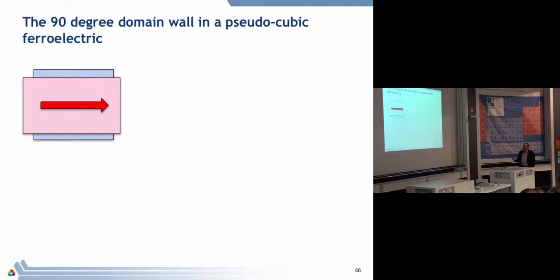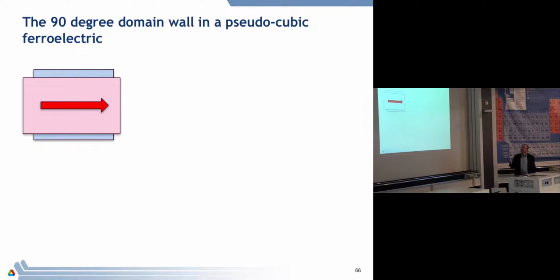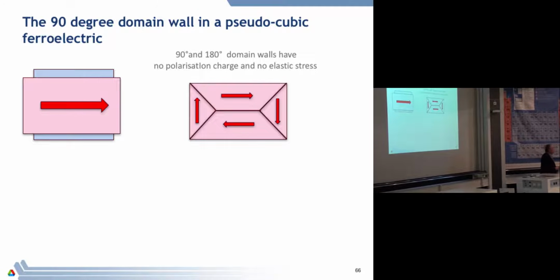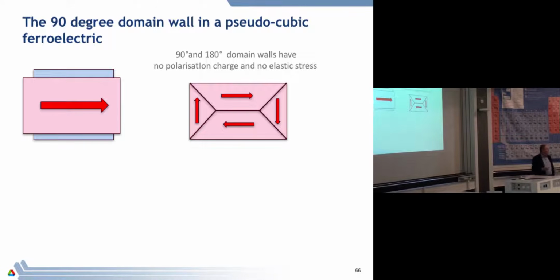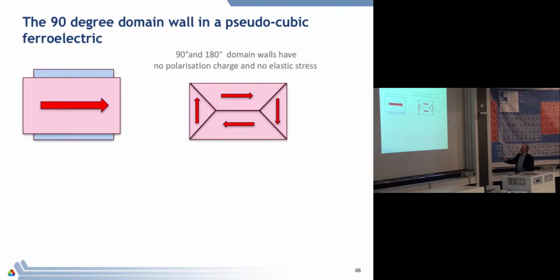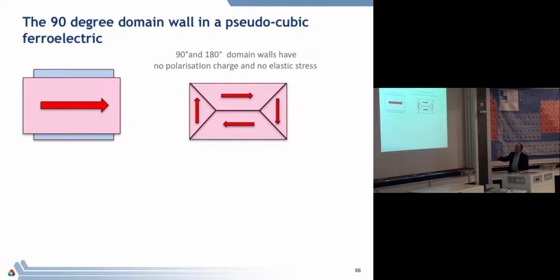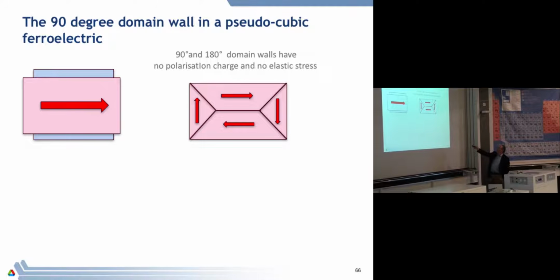Now, actually, you very rarely see single domains. Typically, in a crystal, you see something that looks like that, sort of these letterbox pictures, which consist of little domains. These can be large, they can be small, but I'm imagining that they're pretty much macroscopic, and they will form in a material like this in these kind of patterns. Why do they form in these kind of patterns? Well, there are 2 reasons. So here I've got a polarization. Here I've got a polarization going the other way, and you will notice that this is head to tail.